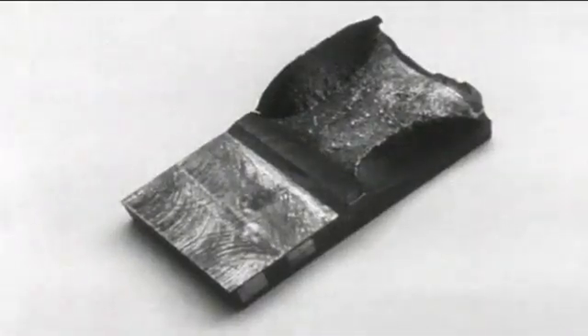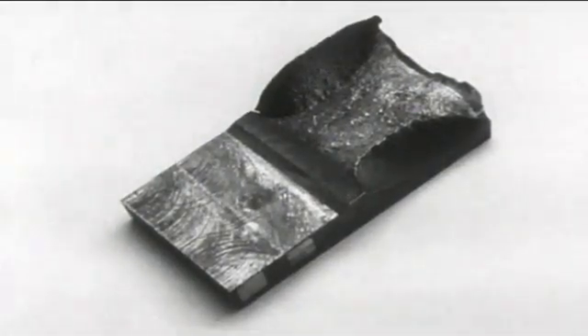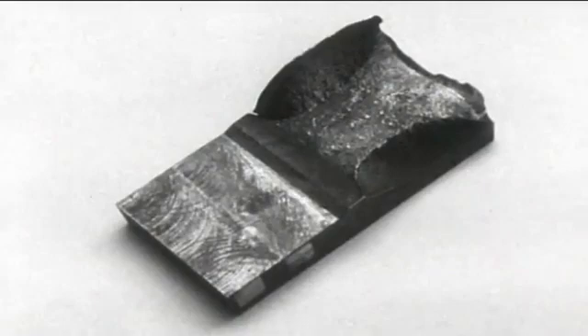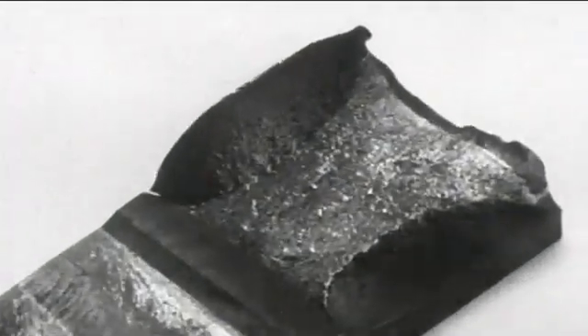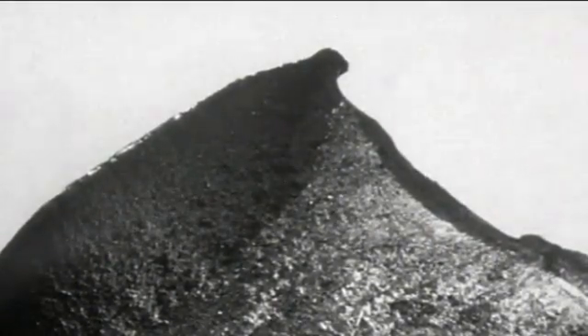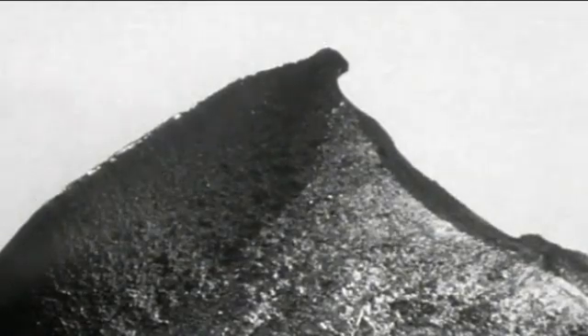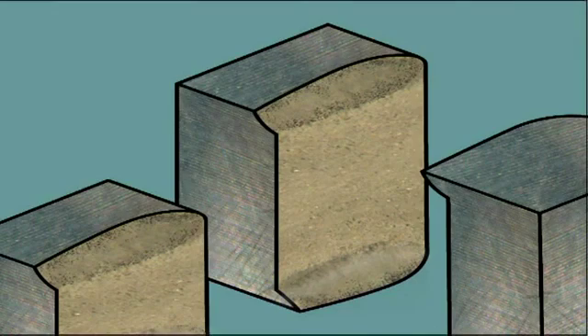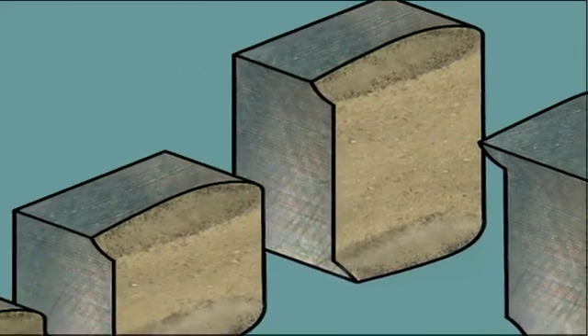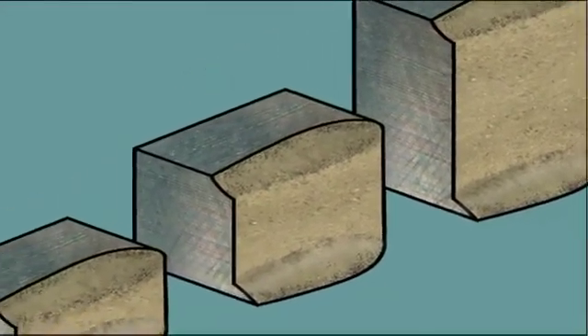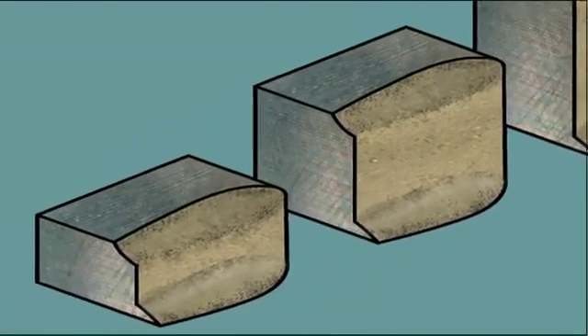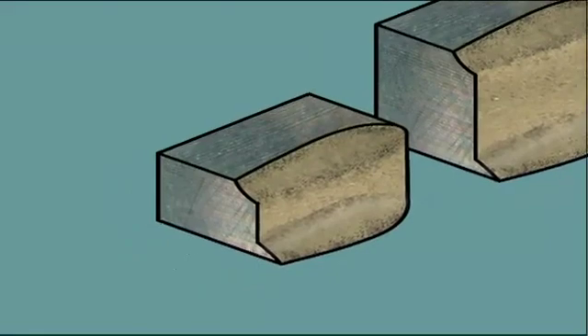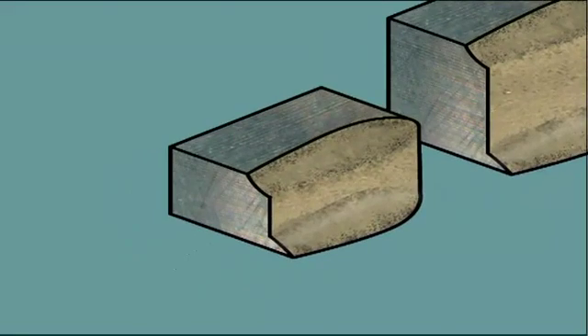In thicker specimens, this effect only operates near the free surfaces. Consequently, near the surface, we see the fracture face turn through 45 degrees to form shear lips. This phenomenon is important because the shear lips absorb more energy than the central flat part of the fracture. In a very thick specimen, a large proportion of the fracture will be flat. But in a thinner specimen, although the size of the shear lips won't change, the proportion of the fracture occurring under conditions of plane strain will be less. Consequently, a greater proportion of the fracture will be plane stress.